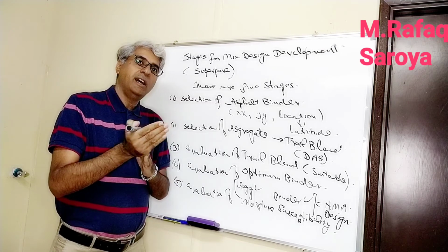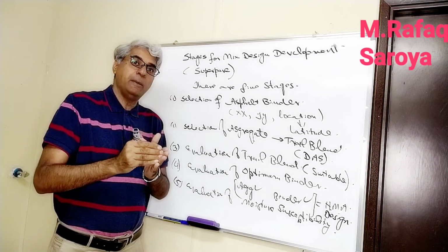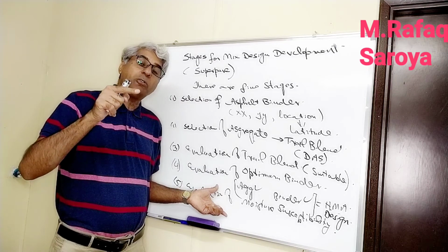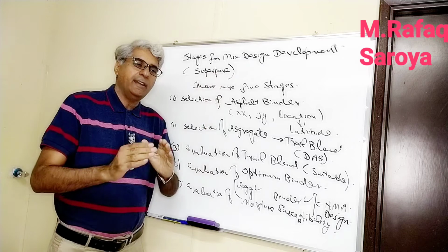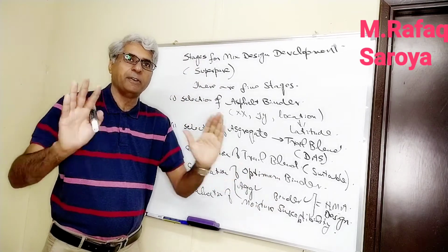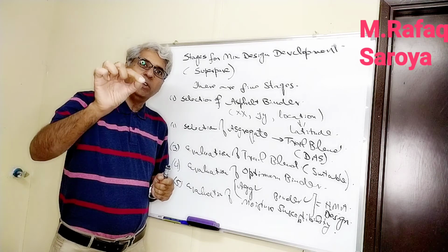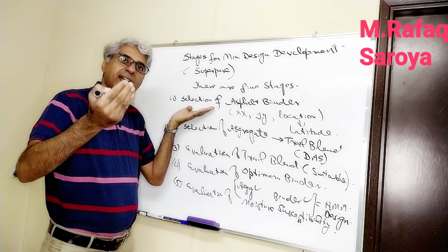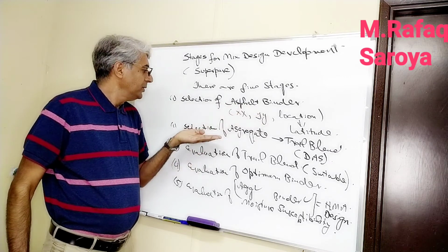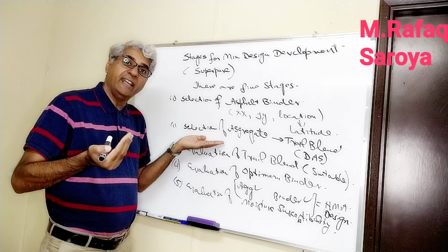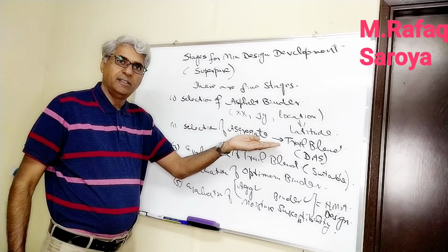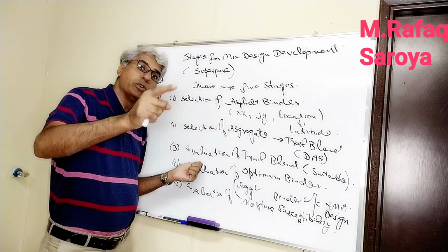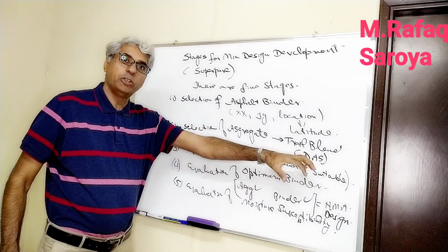Okay, how susceptible to moisture is the relationship between our selected aggregate and binder? Here, certain tests are performed. If those tests satisfy the properties of the Superpave, then the calculation done over here will be considered final. So let me explain in a very precise way. First of all, we will make the calculation for the selection of our asphalt binder. We will make the blend of the aggregates known as the trial blend. This trial blend is the design aggregate structure. From these trial blends, we will select the most suitable one in the evaluation of the trial blend.